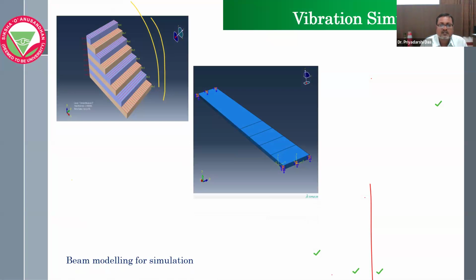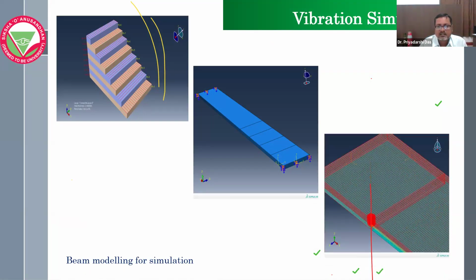Then here the cracks have been formed, assigned with the cracks. And in Abaqus, there is a special case that we can provide the cracks at different regions. For that crack region, you get where the concentration is higher, but through that mesh size,